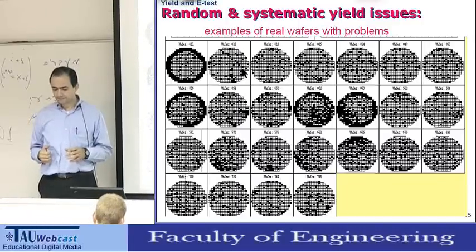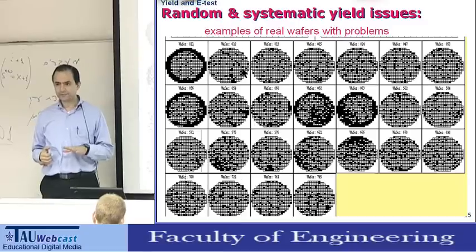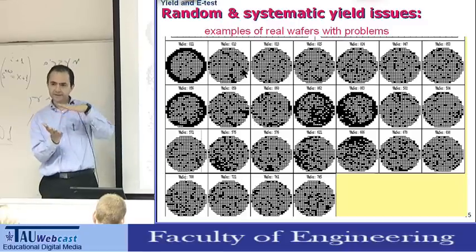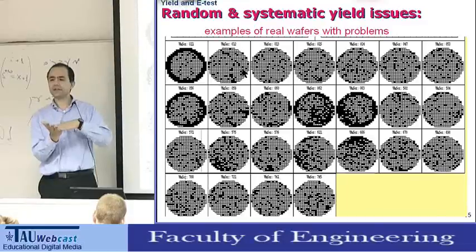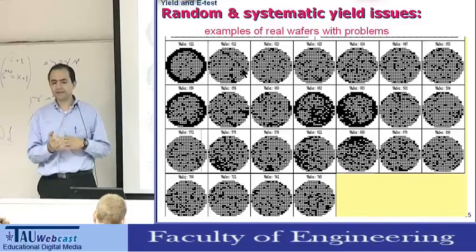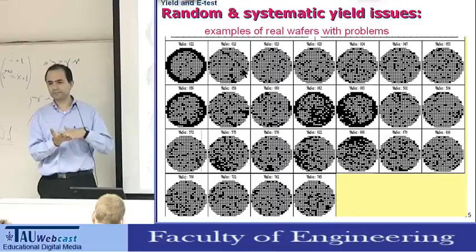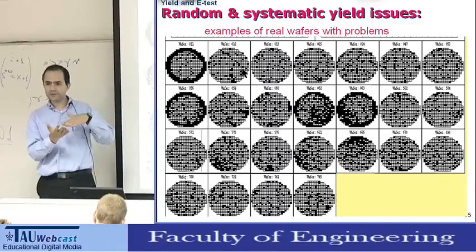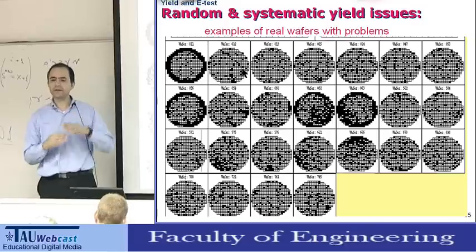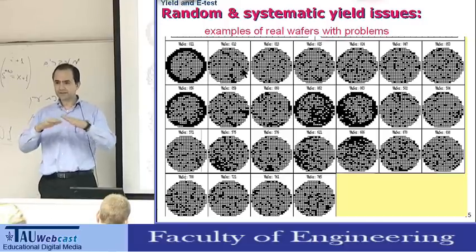Because at the edge of the wafer, the polish pad gets... the edge is an area where the pressure is not continuous. The edge of the wafer is pressing harder than the center. In the center, all the areas next to the centers are similar.